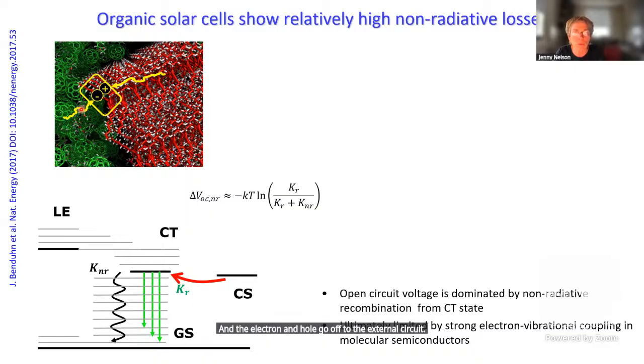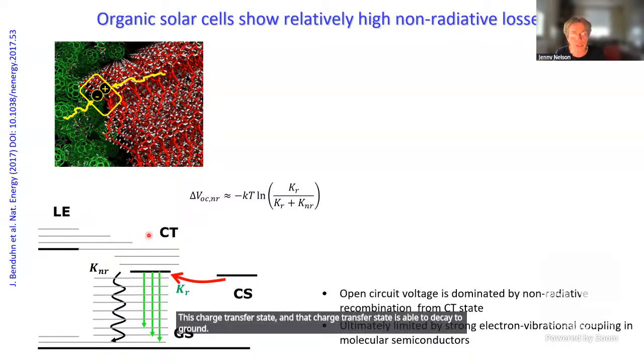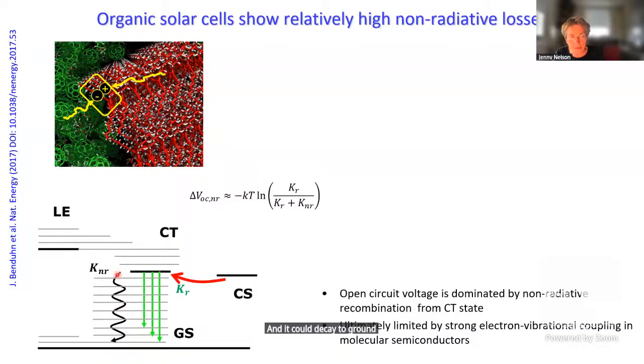Now, the process that we want to avoid is when those two charges come back together, and the place that they can do that is at the interface. If they come back together at the interface, they can form this charge transfer state, and that charge transfer state is able to decay to ground. It could decay non-radiatively by giving out vibrational quanta or phonons, or it could decay radiatively by giving out photons.